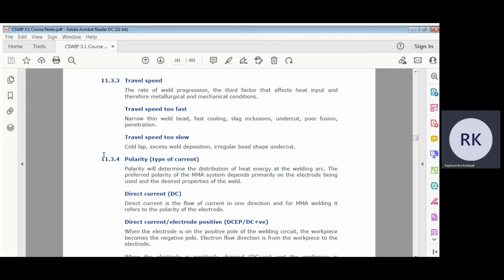Travel speed too fast gives a narrow, thin weld bead, fast cooling, slag inclusion, undercut, poor fusion and penetration. So if you do too fast welding, all this will happen. And if the travel speed is too slow, then you will have cold lap. That means thick welding will happen. Excess weld deposition, that means a very big weld bead will be made. Irregular bead shape will also happen, and undercut will be there because it is a very thick bead. Whenever there is a thick bead, undercut will surely be there.